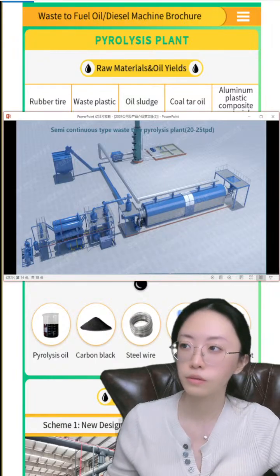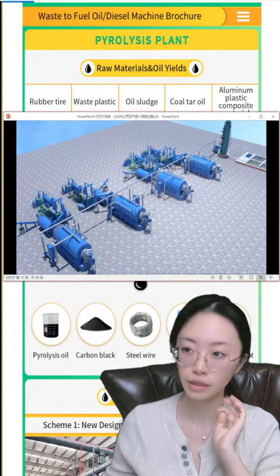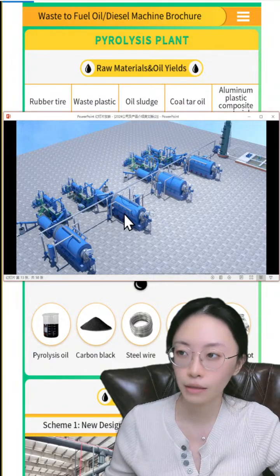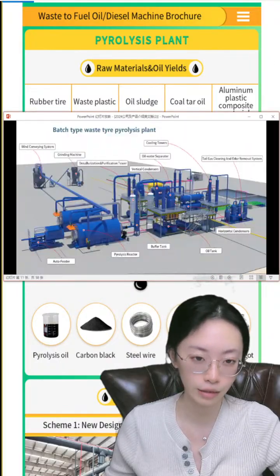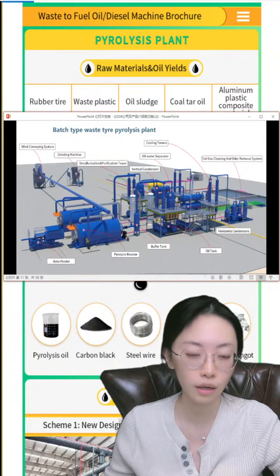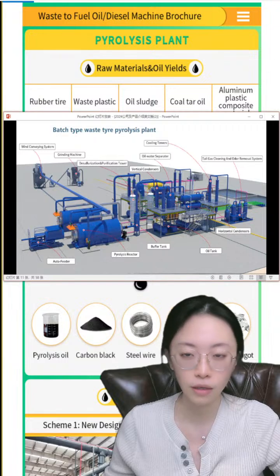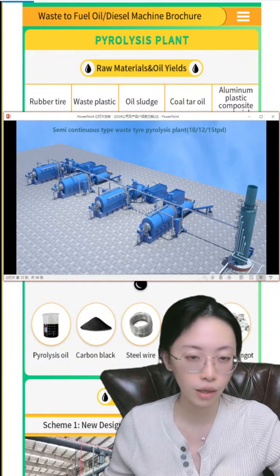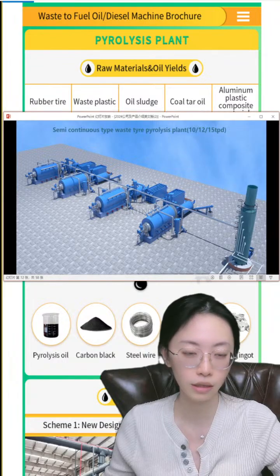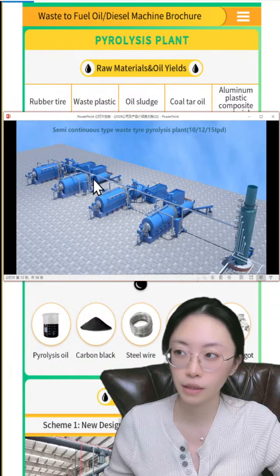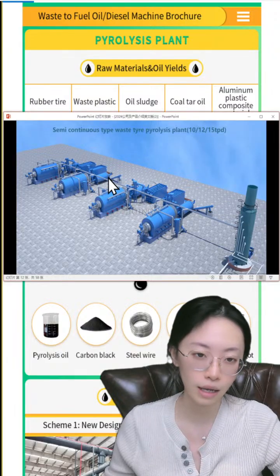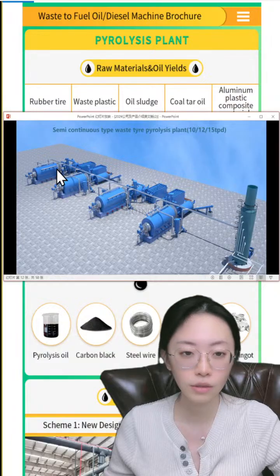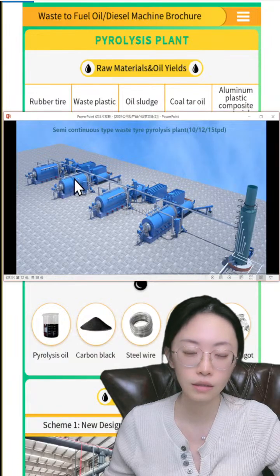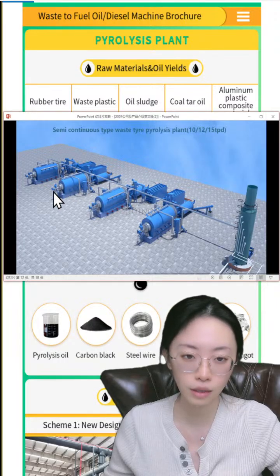Here is also the semi-continuous one. The biggest difference between the batch type and the semi-continuous is that with the batch type pyrolysis plant, we need to cool down the reactor and then we can discharge the carbon black, because it's safer. But with the semi-continuous, we can discharge the carbon black at a very high temperature in a sealed environment and compress it into this small reactor, and it can be naturally cooled down. So we don't need to cool down the whole reactor, and when we slag out the carbon black, we can feed the next raw materials directly.